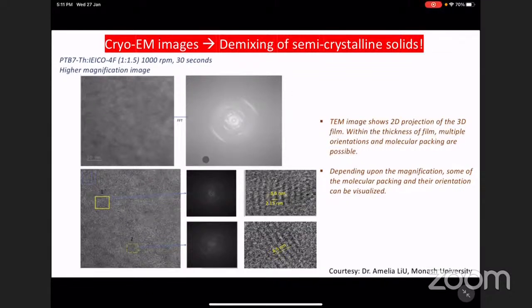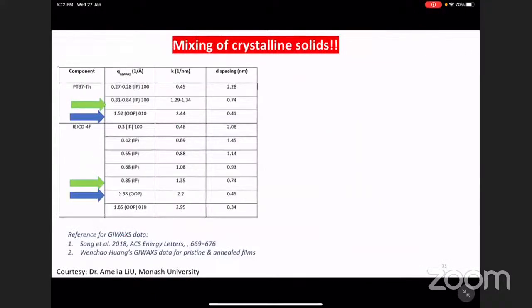These are the FFT, which shows very nice diffraction spots. And all these things suggest that these non-fullerene molecules and the PTB7TH both have very good packing on the individual levels, or whether they are doing something on the intermixing side or not. That is a question which we are still trying to understand, because the lattice fringes being seen in the cryo-EM data are really challenging to interpret, because almost similar constants come into the picture when we talk about the d spacing or the wave vector related to these q values.